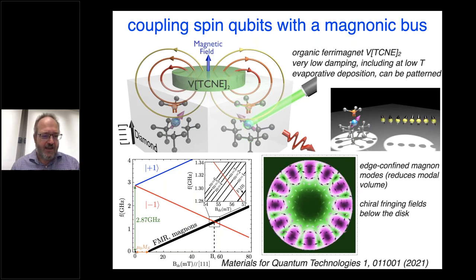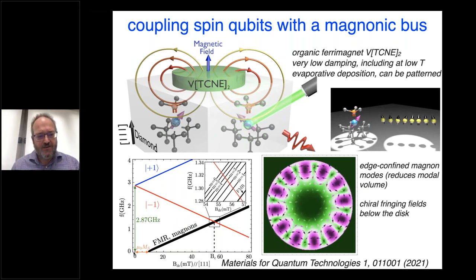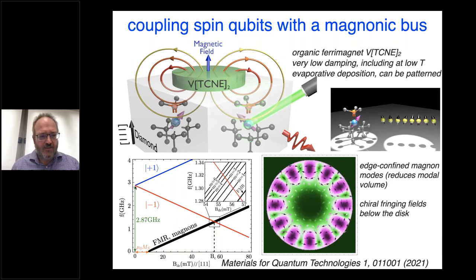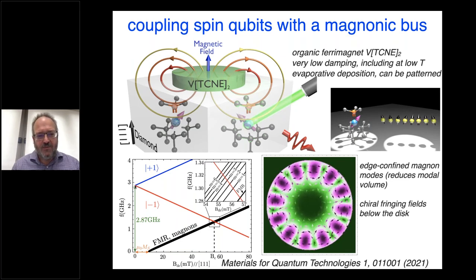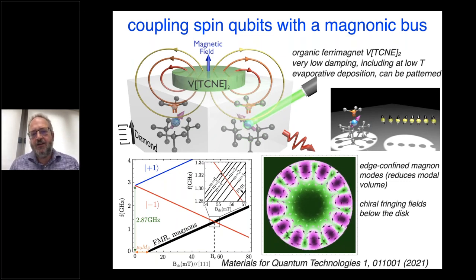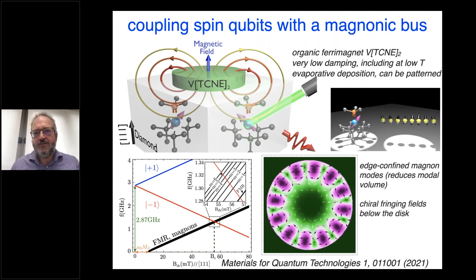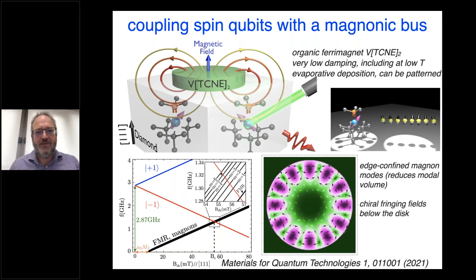Now we also have to have those modes be in resonance with the transitions of the spin center. So shown on the bottom left are the energy states and effectively the transition energies for the NV center. So the zero is down at the bottom, and then the plus and minus one at zero applied field will be degenerate. So you start to apply a DC field along the axis of the NV, you're going to start to split those away, and you can bring that NV transition into resonance with these magnon modes. And those are relatively sharp, as indicated here, so you really need a low-loss material.